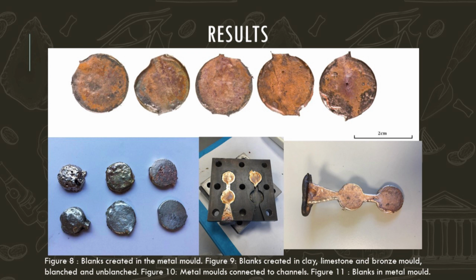Now, the investigation found that the limestone was more than suitable for casting silver copper alloy blanks, and it was actually possible to reuse some cavities in the limestone mould twice or even 3 times before they were no longer viable for casting. And once a suitable stone had been selected, the durability of these moulds would be greatly beneficial to the ancient metallurgist. So it does have obvious advantages of a mould that could take 2 or 3 castings. That would actually reduce the manufacturing time significantly at mints.